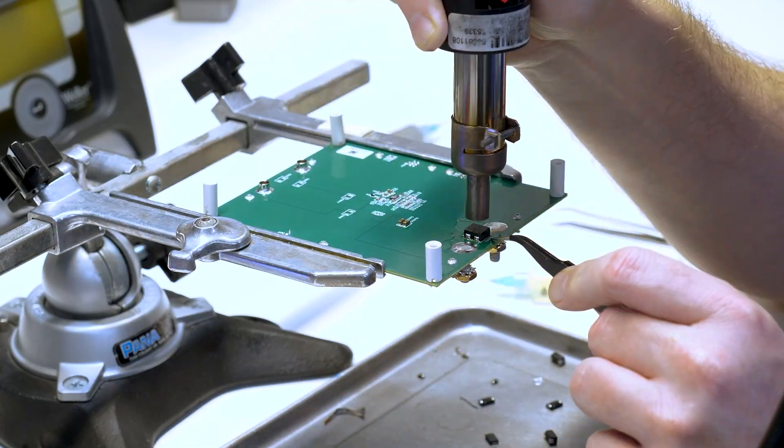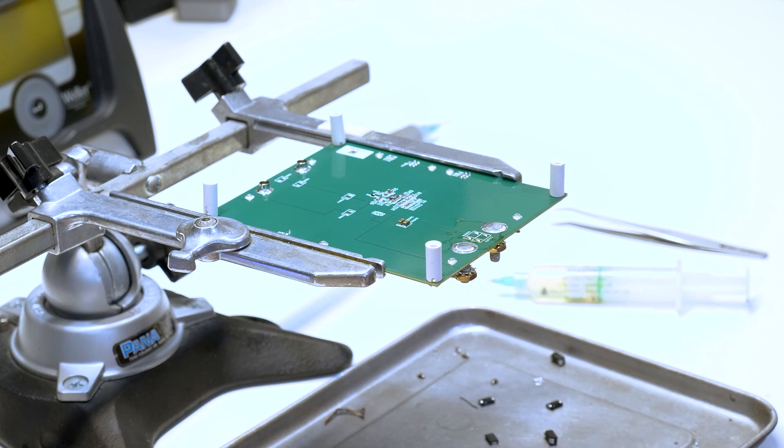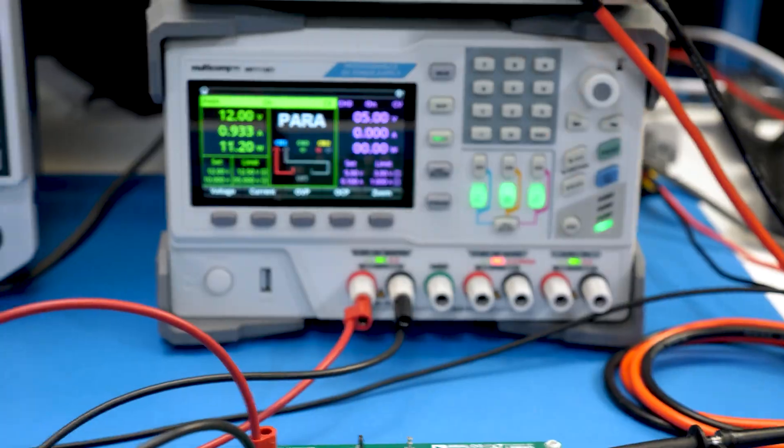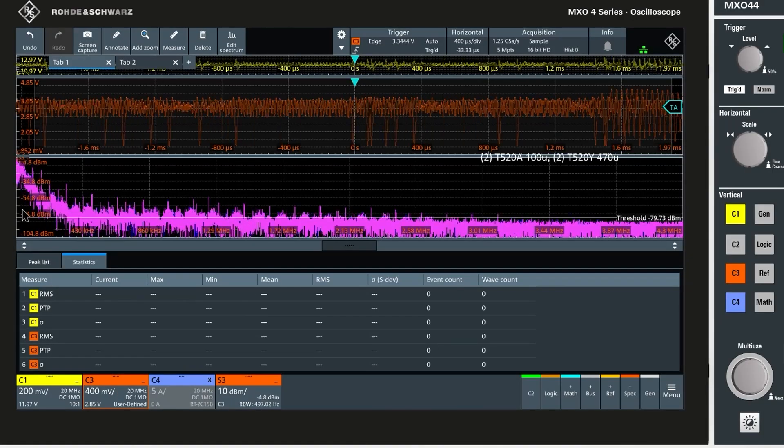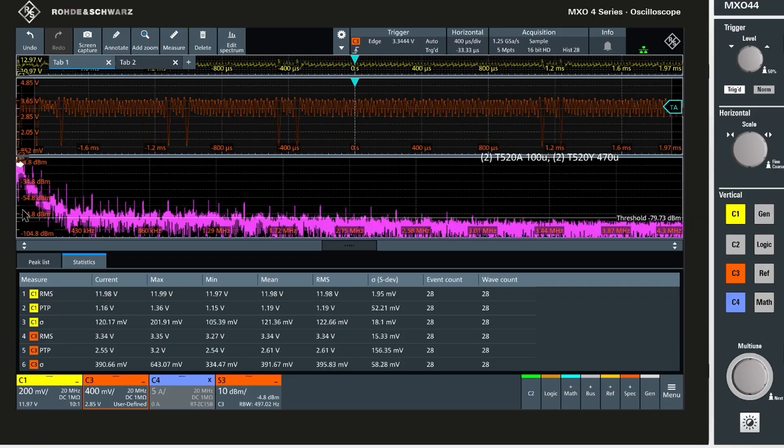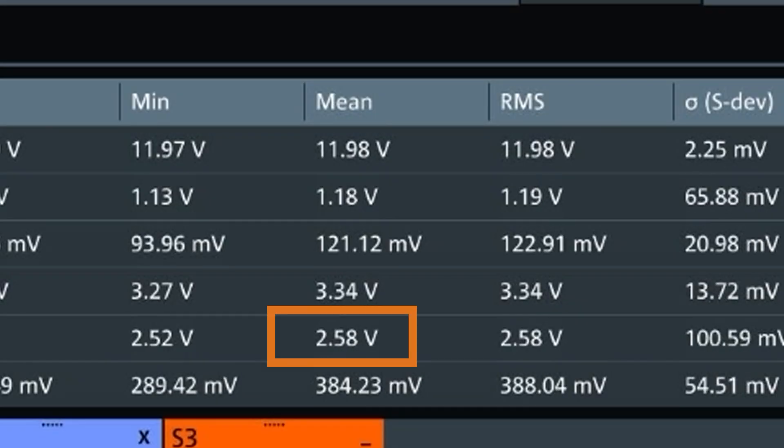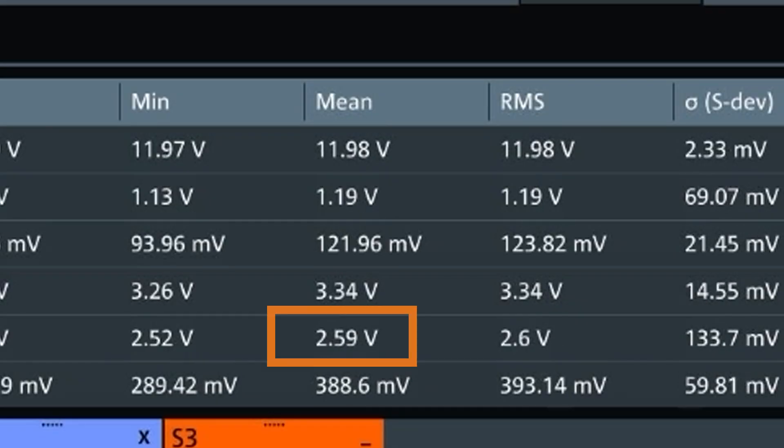Now, you might be wondering, what if the ceramic solution did not have those bulk polymers on it? So, I removed them. And then, I ran the test again at 3.3 amps, and yeah, its ripple is on the order of volts, not millivolts. Either there isn't enough effective capacitance from the 4 MLCCs because of the DC bias effect, or there is not enough ESR on the output for the control loop, causing it to become unstable. Either way, the 4 ceramics by themselves is not a viable solution.